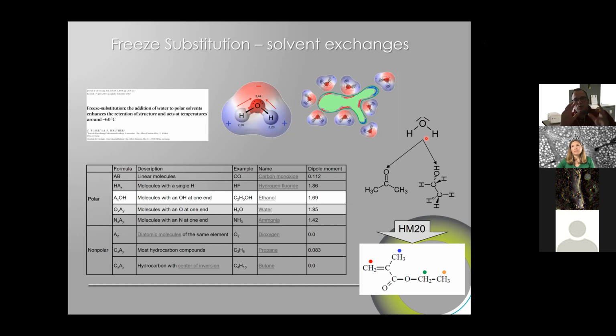Now I'll try to go into the freeze substitution steps. After high pressure freezing your sample or vitrifying it by plunging, what we are going to do is extract the water, the solvent, and replace it with another solvent like acetone or alcohol, and then replace this acetone with a resin. We use this acetone or ethanol step because the resin itself will not remove the water on its own, at least not the ones we're using in our labs.